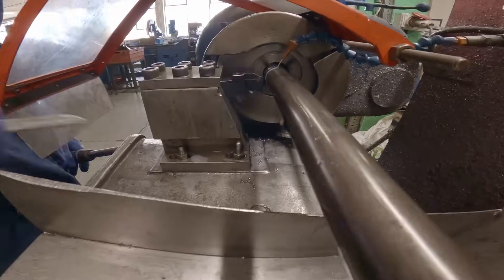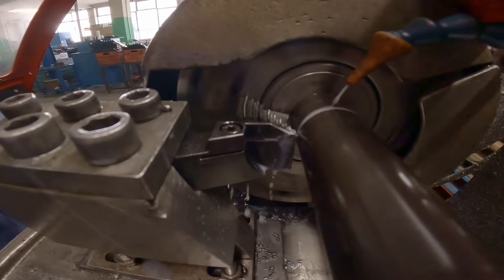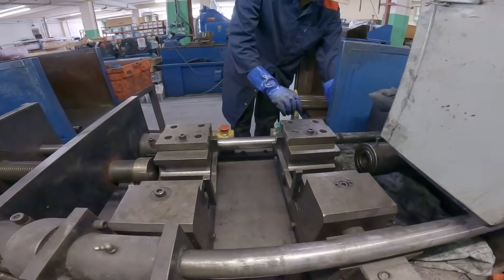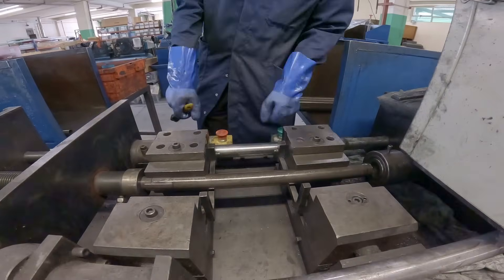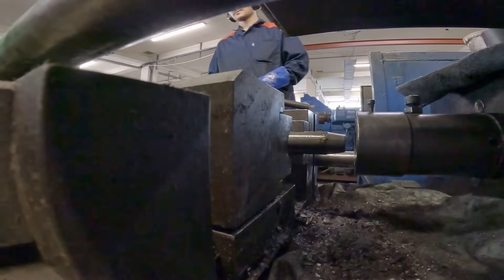The first step is essentially reducing the diameter to bring it to a workable size. The raw material is cut into short pieces, which will then stretch as they're drawn and butted. To bring the material down, first we must nose the tubes — essentially dome the end of them so that they can be pushed through our draw benches.